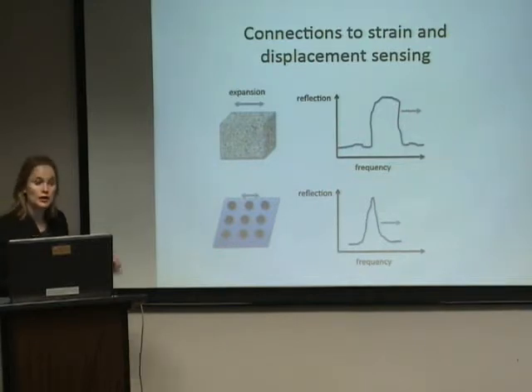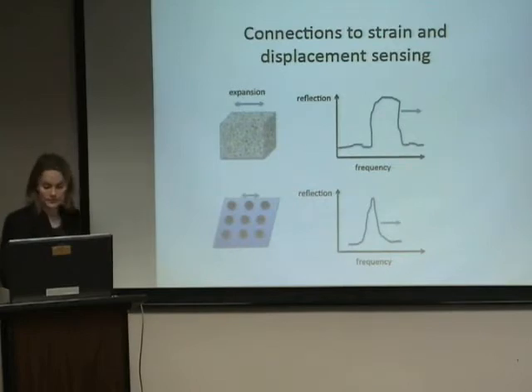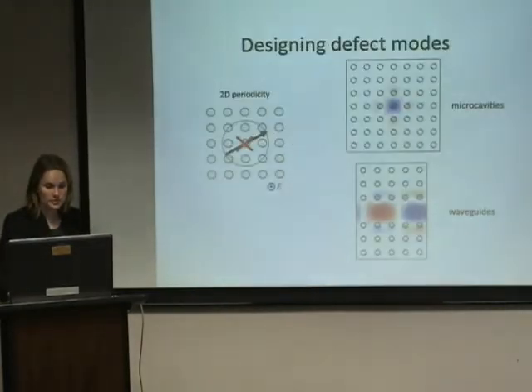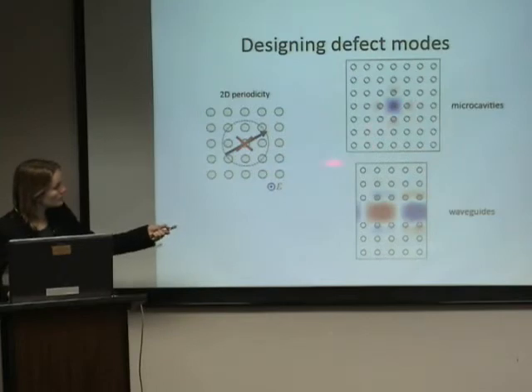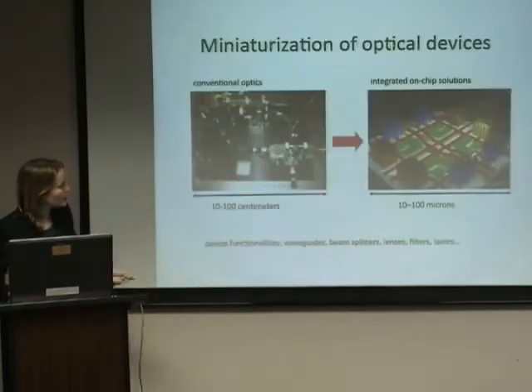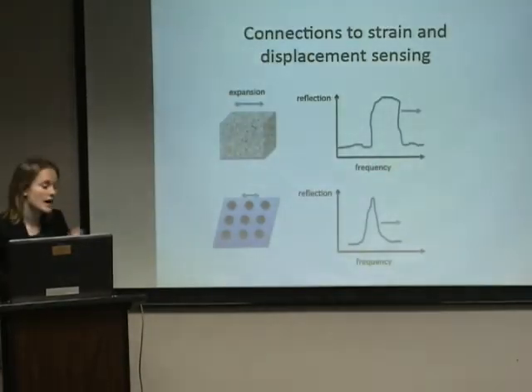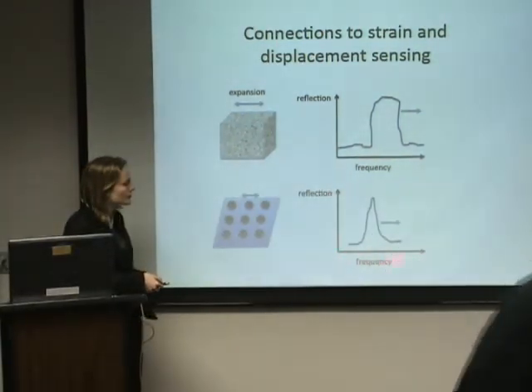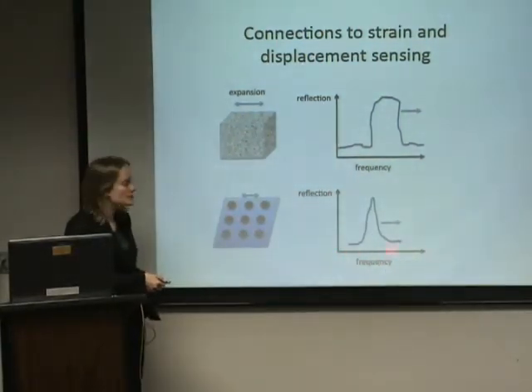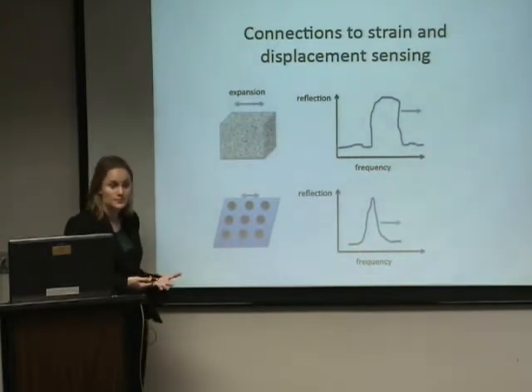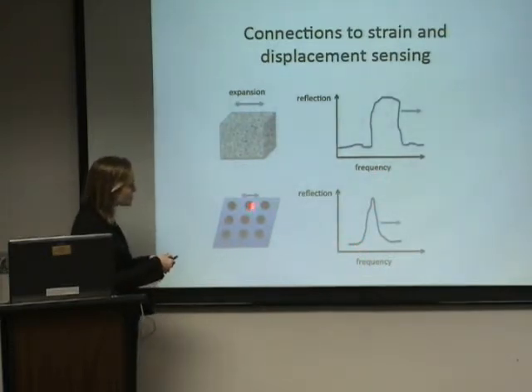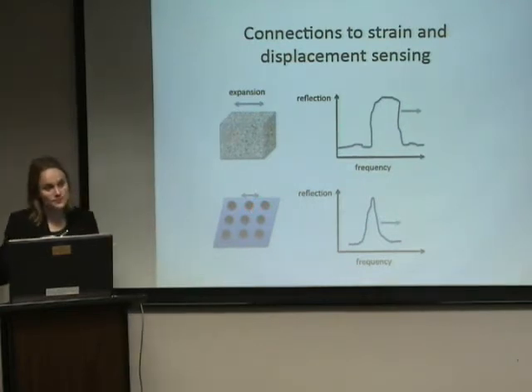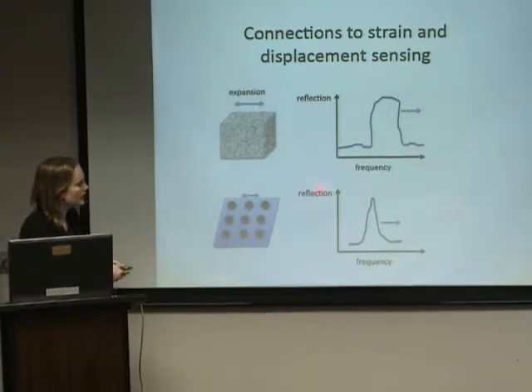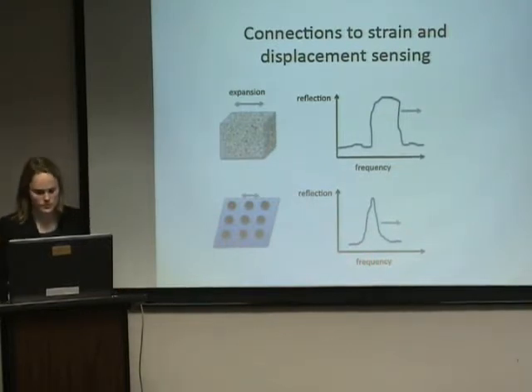So if you take a microcavity element, like the ones you saw both here and here, all of these microcavities have a similar feature: if you look at their reflection as a function of frequency, they have a resonance in the reflection. Similarly, if your actual resonator changes shape, the particular frequency of the light that can travel around and be supported by that resonator shifts, and so you get a resonant shift. And this then is a second sensing mechanism.